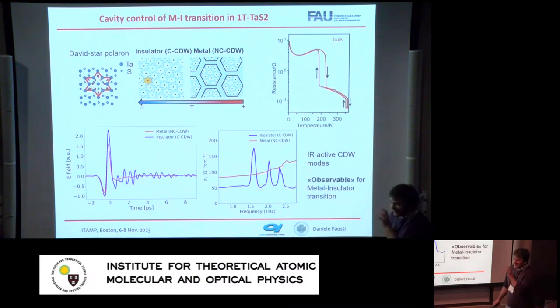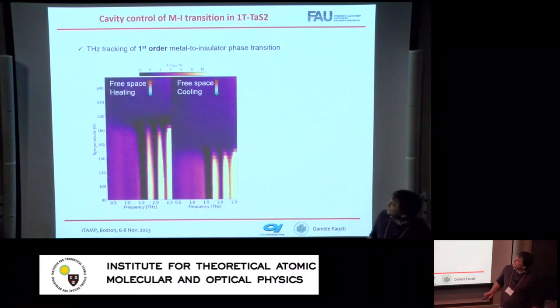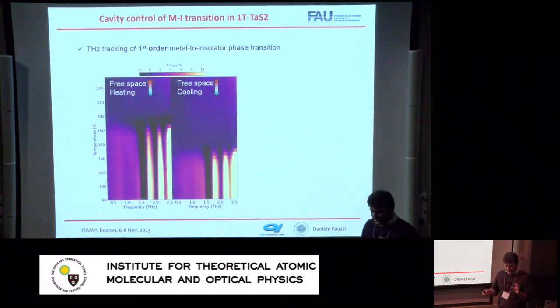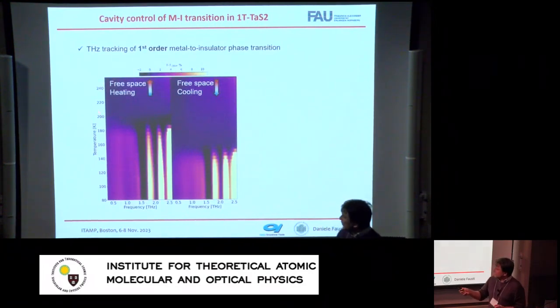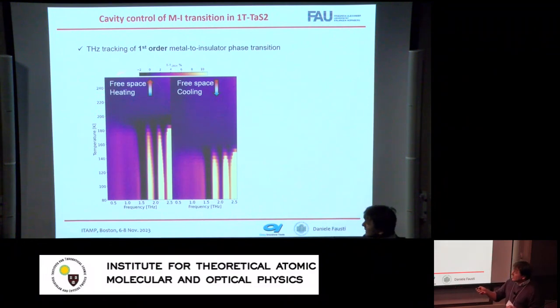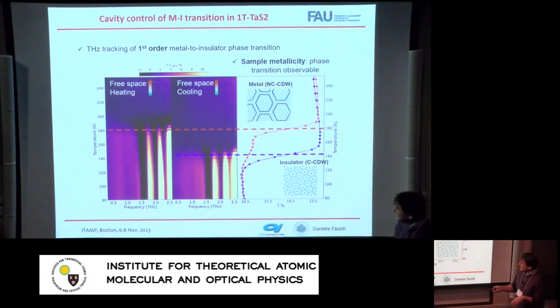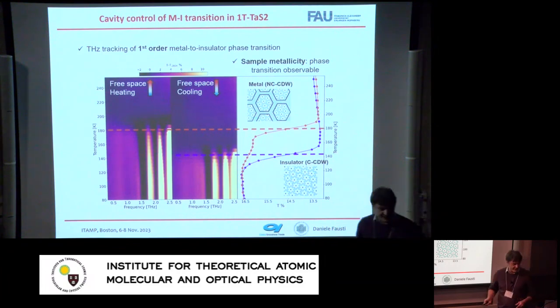So we have an observable. We can measure this phase transition, and we fix our cavity so that we can measure the temperature of the support of the sample. We can cool down the system or heat it up, and we see a transition from a dielectric response which has three sharp phonon resonances. I can map the hysteresis as a function of the temperature of the support of my sample, and basically I can see a transition from an insulating state where I have sharp phonon modes to a metallic state where the transmission is featureless, associated to the response of the material.